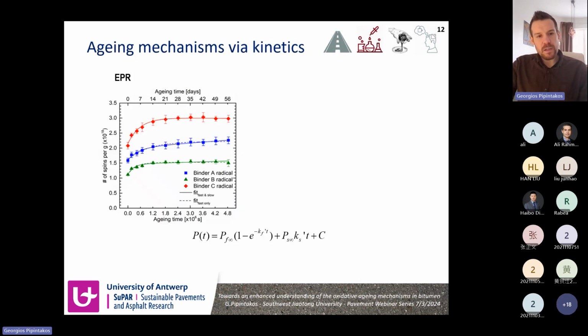And you can see on the left here that the number of spins of the carbon-centered radicals followed again a more rapid increase in the beginning, followed by an almost constant slope or even a plateau, as can be seen. And this means that we tried again to fit them with the same model, the first order kinetics model.